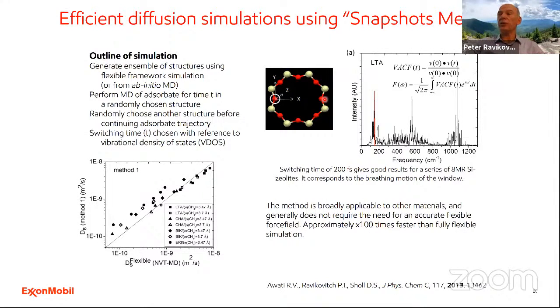In this case, you decouple the flexibility of the framework from molecular diffusion, and if they can be decoupled, this method is very efficient. And the frequency with which you need to switch these snapshots should correspond to the frequency of vibrations of the window, which is usually a low-frequency vibration, which you can calculate by, for example, the so-called vibrational density of states. And it basically gives you the frequency with which these windows fluctuate.